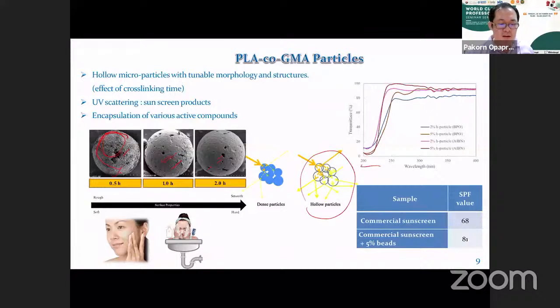So we measure the transmission spectra of our materials that we mix with sunscreen products, and then look at their transmission performance. We can see the clear difference in the UV region, that our hollow particles here can help improve the blocking of UV light. And if we convert this into SPF scale, we can see that if we use only the base sunscreen, the SPF is 68, and if we add only about 5% of this nanoparticles into the products, we can improve the SPF value here.